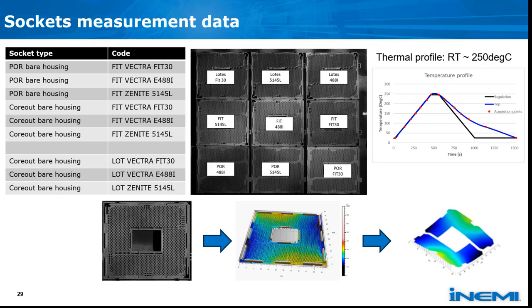So for our subject, we have been measuring the different designs and materials for the sockets, and being able to compare them. They will measure 9 by 9 through a thermal profile from 25 degrees C up to 245 or 250 degrees C, then back to 25 degrees C. And we were able to capture the full socket shape, and then we were just masking the areas which are not good for the analysis, just to get the ROI and the 3D shape of each socket at each temperature.